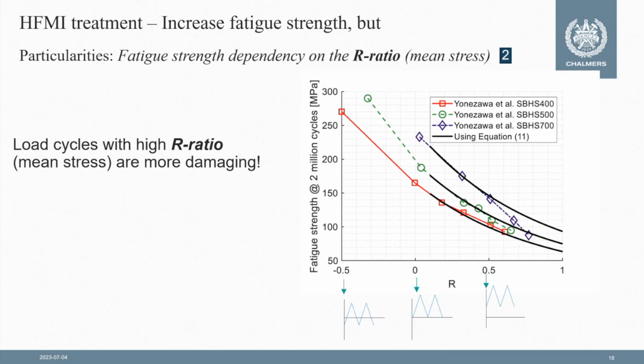Another implication which is important and a particularity that we need to take into account in terms of design is that the fatigue strength now becomes dependent also on the R ratio. While this aspect is not considered when we currently design welded structures in as-welded condition, with HFMI treated details, load cycles with the same stress range, but with higher mean stress or with higher R ratio, will be more damaging than the same load cycles with the same stress range, but with lower R ratio or with lower mean stress. And this influence of the R ratio needs also to be accounted for, of course, in the design. So this is the second implication. In addition to fy, the R ratio needs to be accounted for.